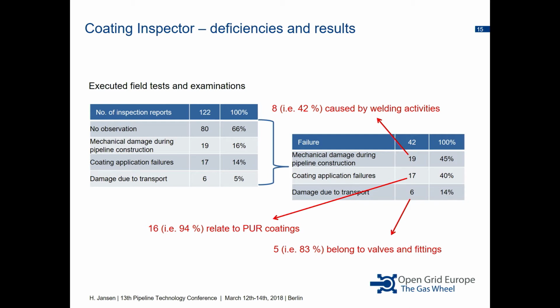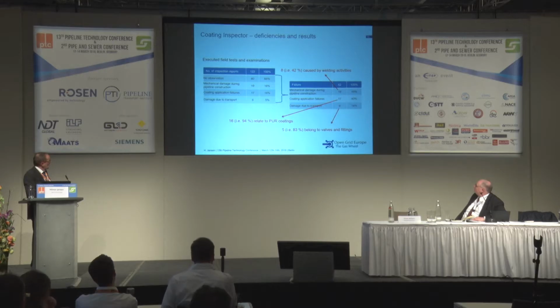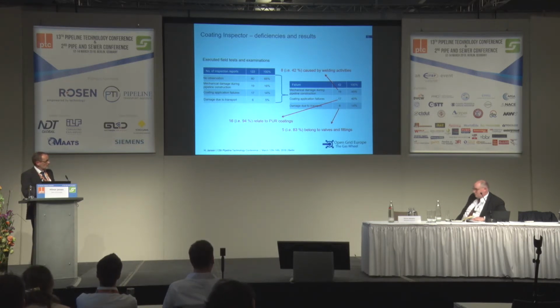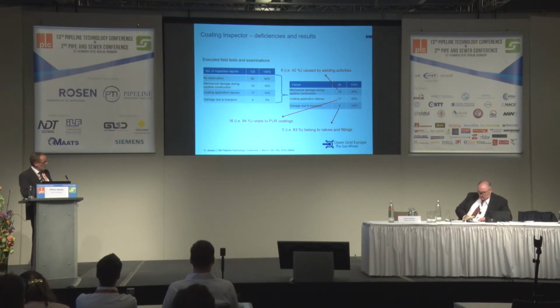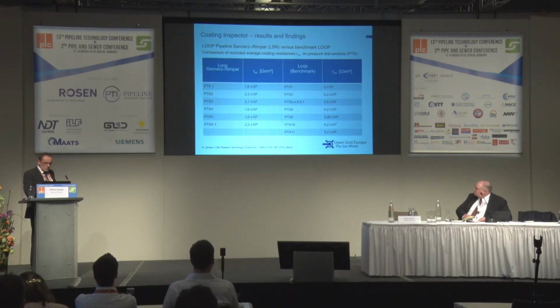Nearly 100% of these coating application failures relate to polyurethane coatings, wrong mixing ratios. The applicators did not consider the temperature conditions on site. Nearly 100% of the damage due to transport belong to valves and fittings. We saw this photo with the fixed chains where the metallic chains have fixed the valve on the lorry.